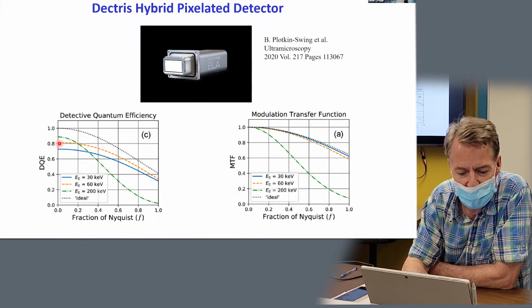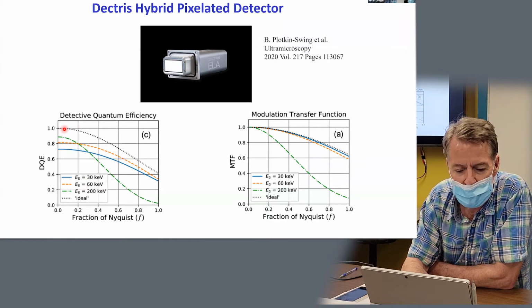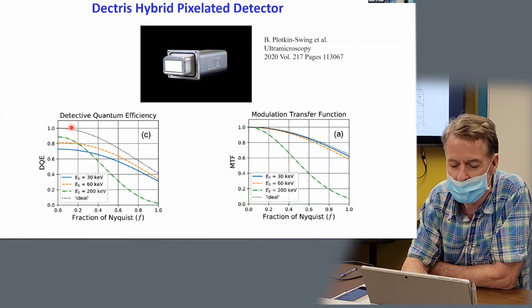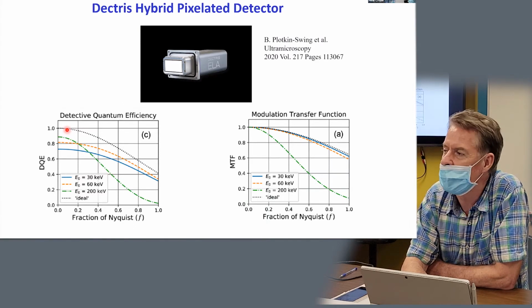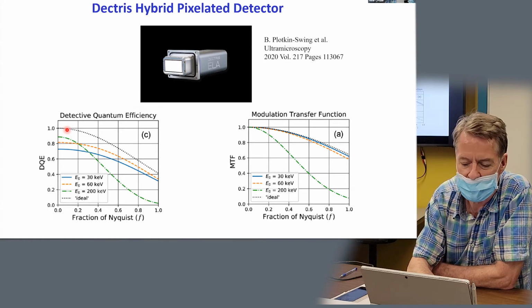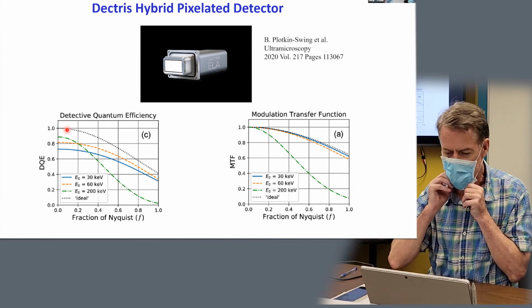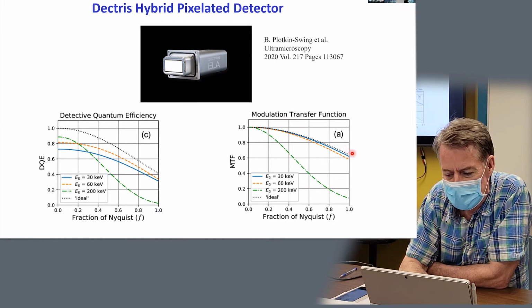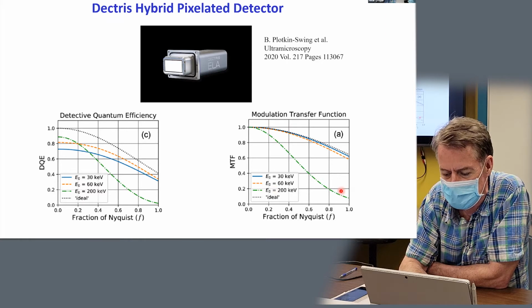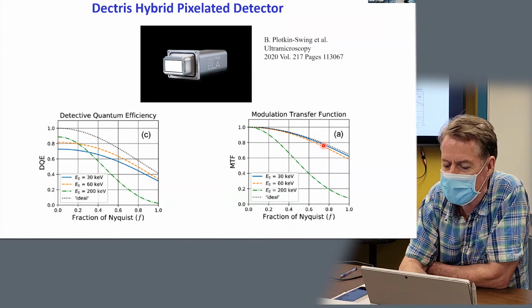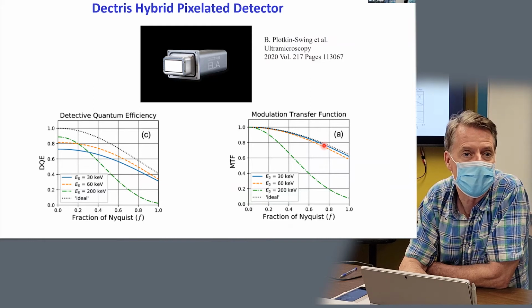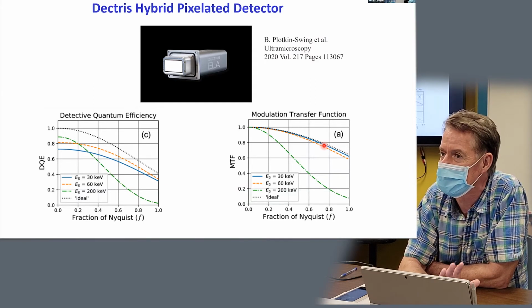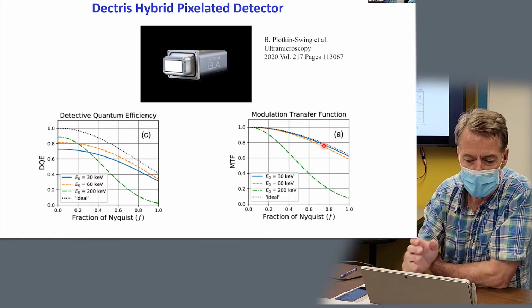What I want you to point out is that our microscope running at 30 or 60 kV, if you look at the yellow curve and the blue curve, they're almost matching the theoretical maximum. So the differences in efficiency that we have on our detector are on the order of less than 20% away from the theoretical maximum. So that's really fabulous performance. And then if you look over here at the modulation transfer function, the dotted black curve is the ideal modulation transfer function, again plotted as a function of spatial frequency. And again, our microscope is the blue and the yellow and the dotted orange curve. And you can see that they're almost exactly following the theoretical limit. So that's one of the reasons why we're so excited about this detector, because it's really as close to an ideal detector as you could probably expect to get.